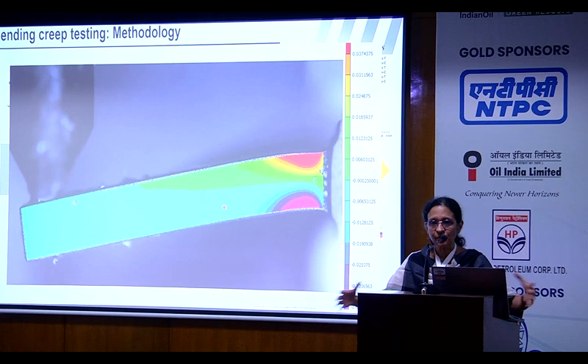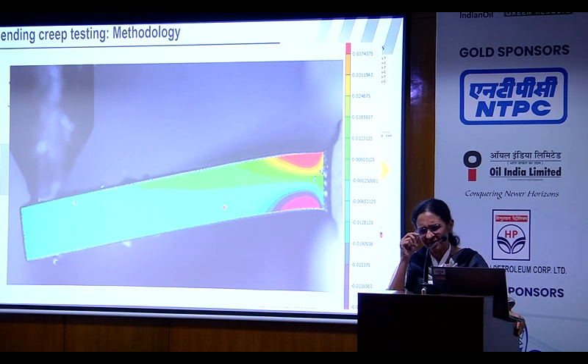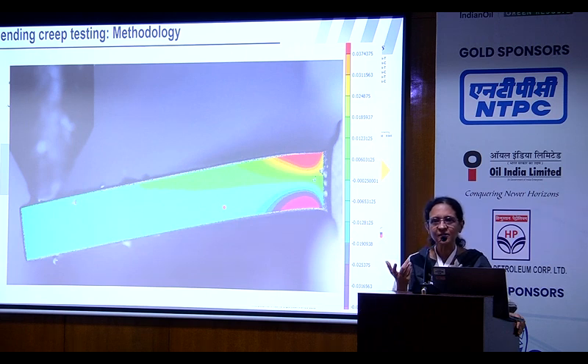Imagine not having to do multiple experiments, and you're also able to look, especially in the context of location specific properties. Let's say in a rotor, I cannot take a rotor which is functioning and cut it up and weld it back again and put it. Already you're looking at the structural integrity. So we take very tiny specimens, establish in the lab the equivalence, prove with standard ASTM test specimens, and the beauty is the high throughput.